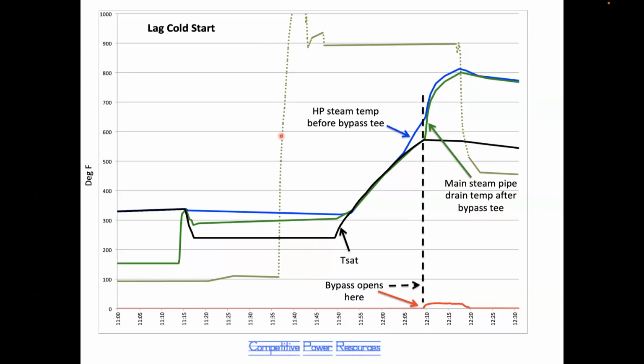Gas turbine again fires here. Superheater outlet and downstream pipe temperature, they're following saturation. There's no steam flow in those pipes in order to warm them. So the superheater outlet begins to get some superheat, but the steam pipe temperature downstream of the bypass T remains cold and at saturation. So when the bypass opens, there's no superheat, and the condensate that has been forming in this pipe is drawn into the valve at this point. The pipe work immediately begins to heat up once the flow path is established by opening the bypass. So it's almost always the cold lag start that causes the erosion in the bypass valve.